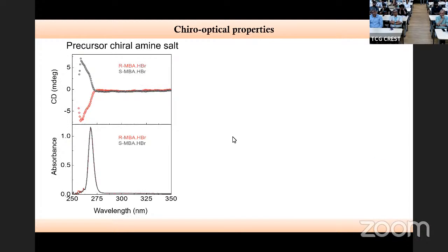Now, this is only the molecule. If I look at its chirality, the absorption of the R and S variety, the two different chiral systems, they're of course identical. But if I take only one of them, let's say R, and take the difference between left and right circularly polarized light absorption, I see a distinct feature that measures the difference between the right and left circularly polarized absorption. And I see a mirror image of that if I take the opposite chirality. And what I would like you to notice is that this organic does not absorb at longer wavelength than 275 to 290. If I see anything on that side, that is contributed by the inorganic part when I make the compound. So we know that chirality coming, let's say below 280 or so, is all because of the organic.